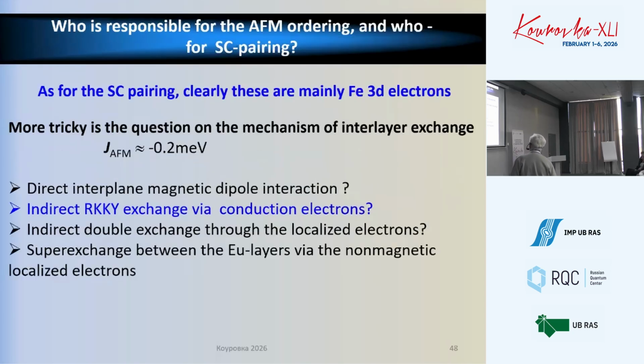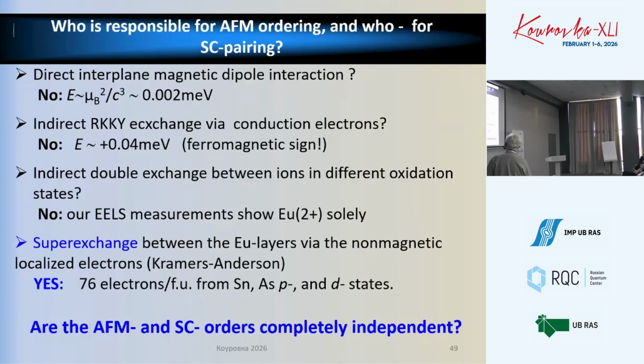To analyze this issue, we have to consider what mechanism is responsible for interlayer exchange. As I said, this can be easily estimated. We need to explain the exchange coupling of minus 0.2 meV, which comes from the Néel temperature, or from the magnetization saturation field. Anyhow, we know the magnitude, and we have to find out the mechanism responsible. We can make estimations, and first, we immediately find that the direct interplane magnetic dipole interaction is 100 times weaker. It is ineffective.